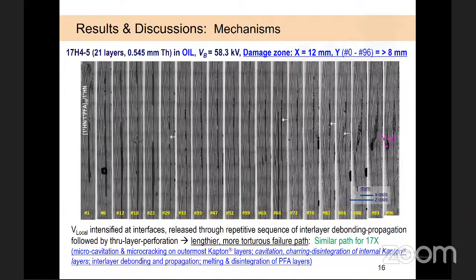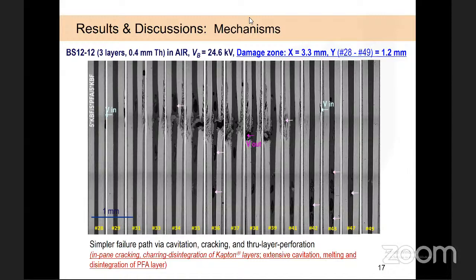This is the sequence of the same 17H4 sample, but failed in oil. They looked slightly different, but basically progressed by the same lengthier and more tortuous failure path. And note that the overall damage zone was much larger than that failed in air. And again, the 17X sample showed a similar failure path. However, we have stopped here because we don't have much time.